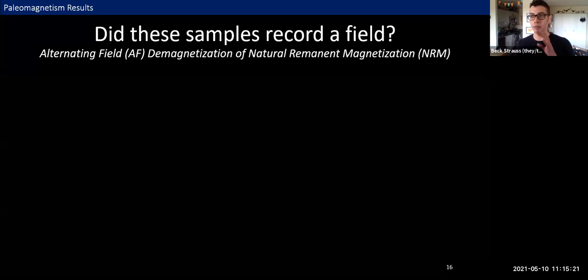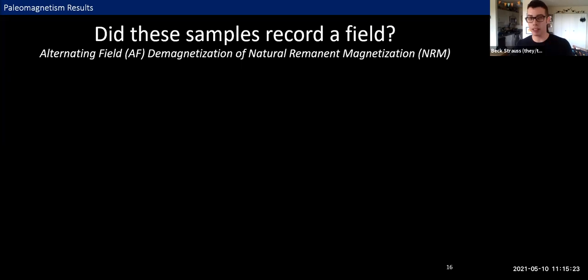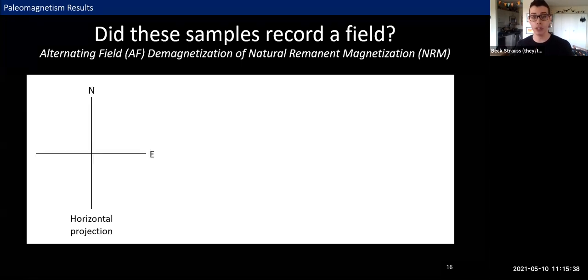Now, the results of these kinds of experiments get plotted in a super weird way that only paleomagnetists do. So I'm going to show you how we plot it, and then I'm going to show you my actual results. We're attempting to put a three-dimensional magnetic vector onto a two-dimensional page. So we start with a horizontal projection of that vector. We've got our north axis and our east axis, and we start out at the NRM, and as we apply stronger and stronger fields, the data tends towards zero as we're removing the magnetic signal.